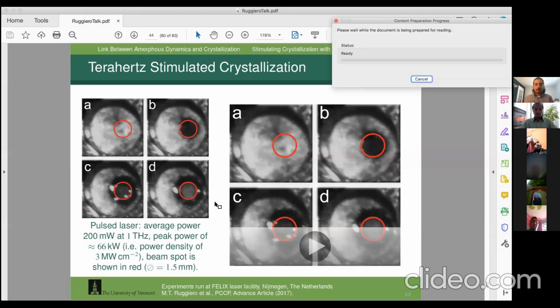So what we did was we took amorphous drug and cooled it down in a liquid nitrogen cryostat to 80 Kelvin, well below the secondary glass transition temperature, where it would be stable indefinitely. We put some temperature probes on it to monitor the temperature.